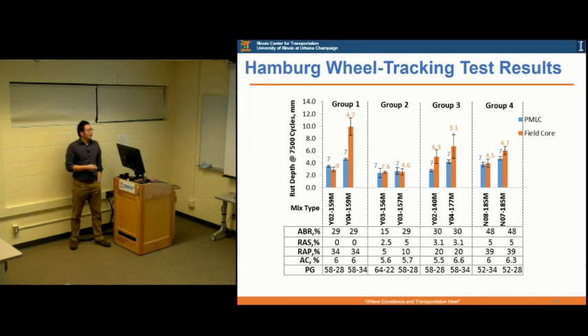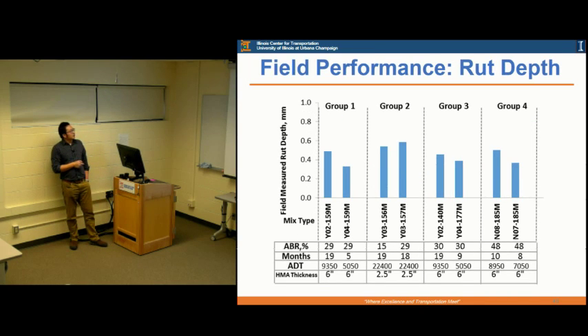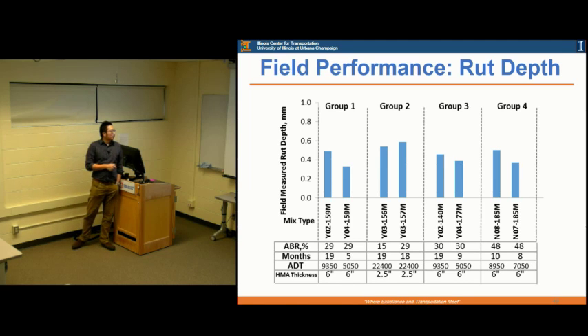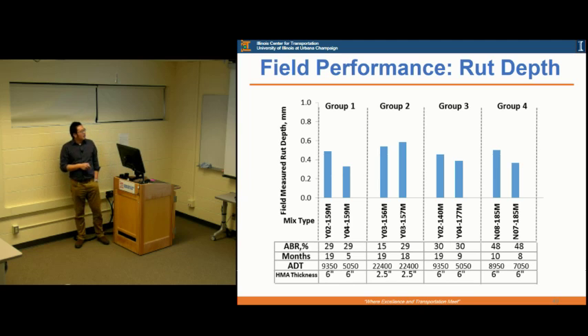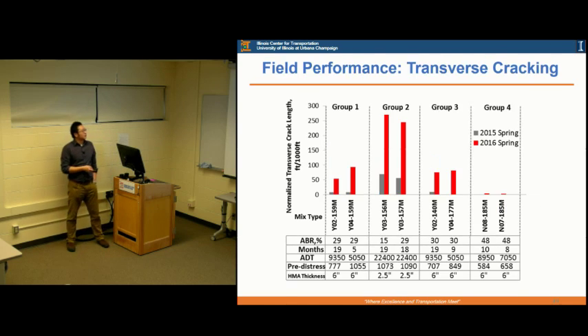This is the field performance where we measure the rut depths, and we put everything here. Even though you see a little difference, they are too small - all the rut depth is less than 1 millimeter, so you barely can see them with the naked eye. This means all the rutting resistance for the mixes is pretty good in the field.